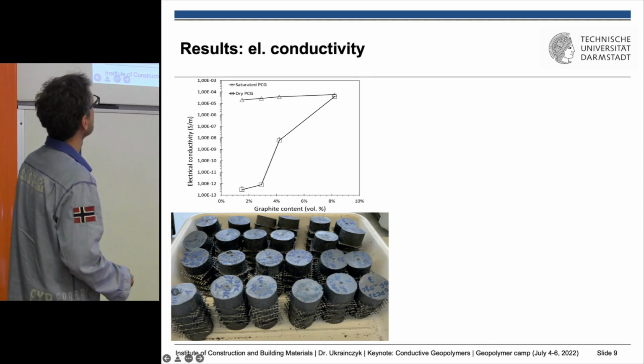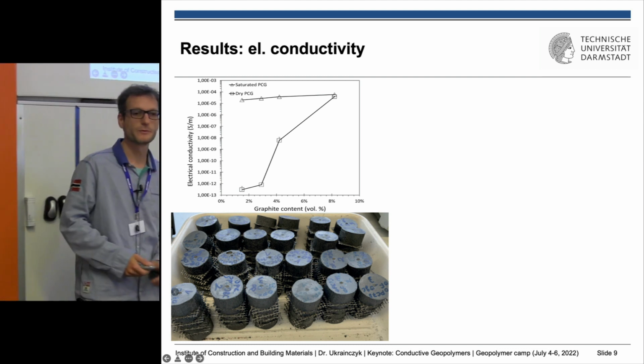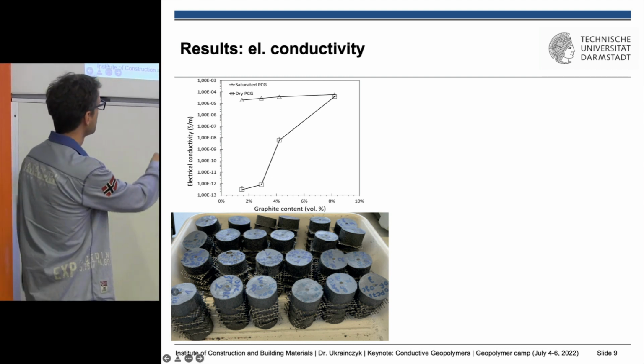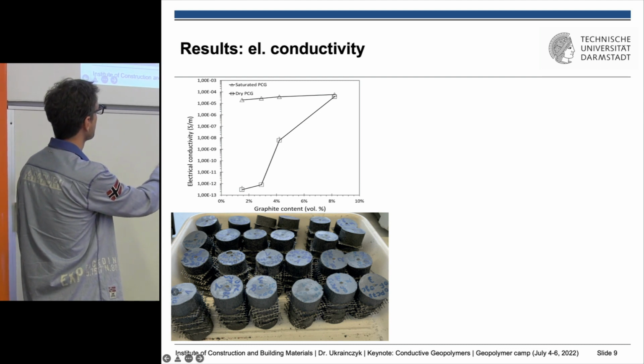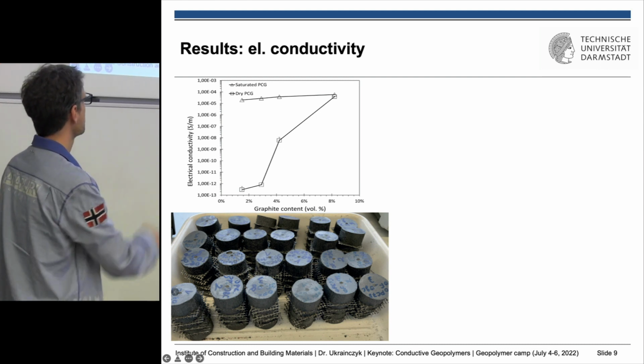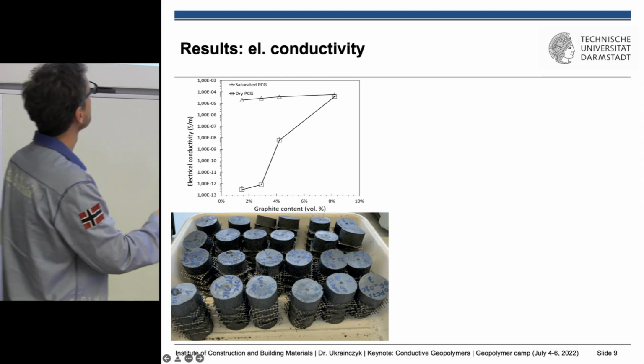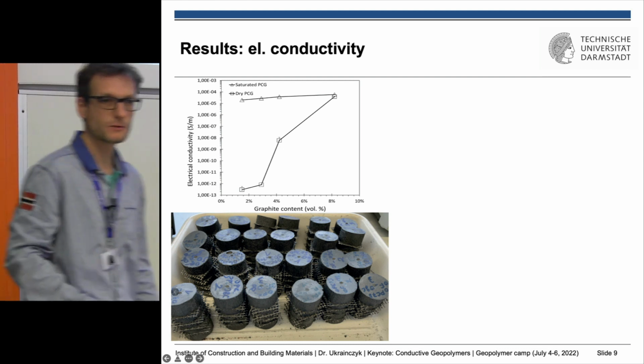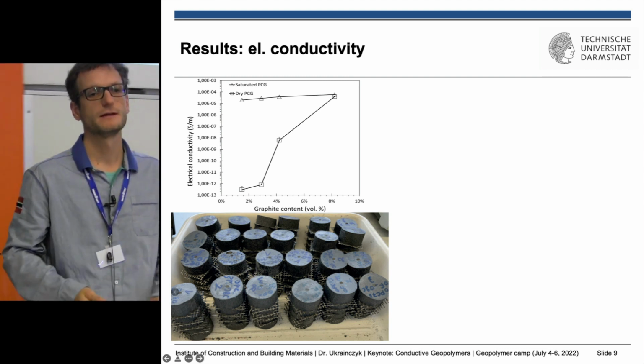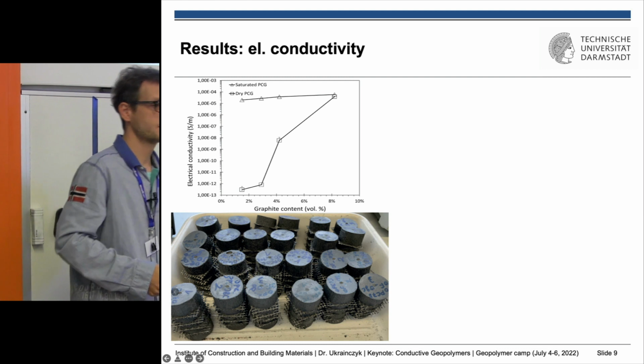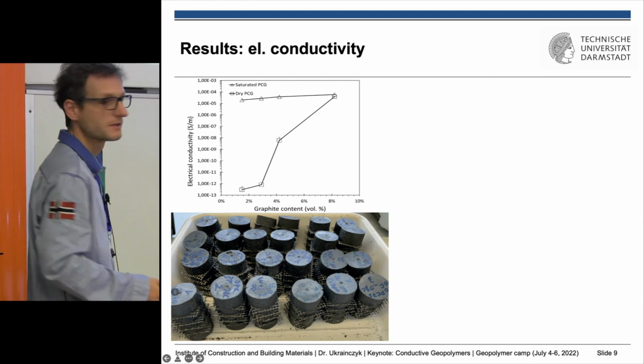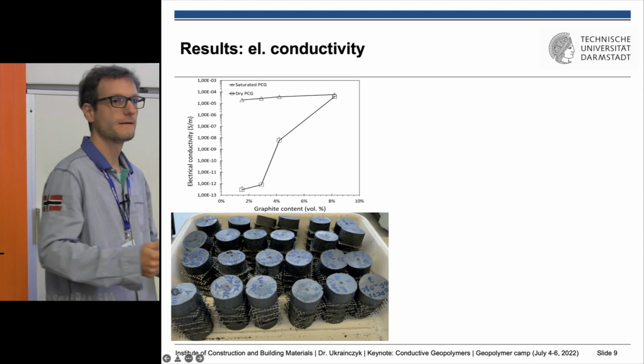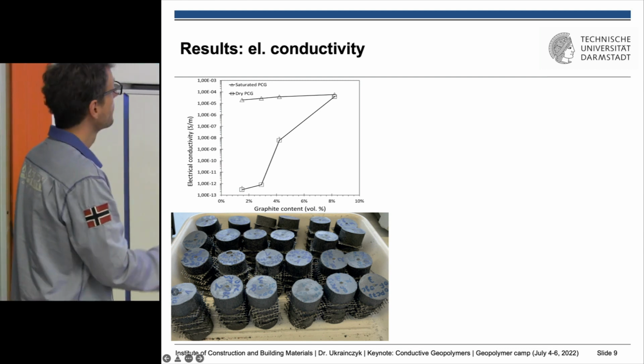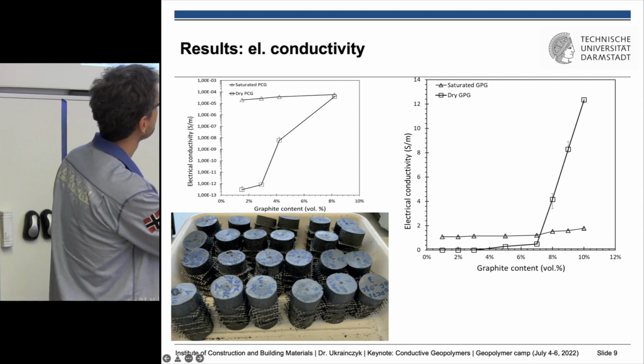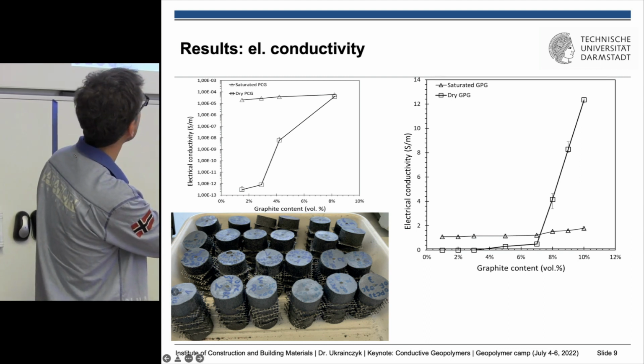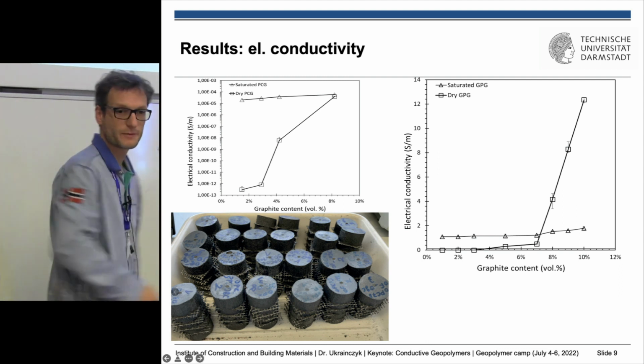So there is electrical conductivity, which we measured. It's a 4-probe measurement. And we can see here 4 electrodes. We also did it with steel electrodes, with meshes, and different shapes. And for Portland cement, they didn't actually percolate so well. So the compatibility in cements to percolate the graphite is much, much worse than for geopolymers. So with geopolymers, they really match with graphite. And we can see that the conductivity is by far 2, 3, 4 orders of magnitude higher.